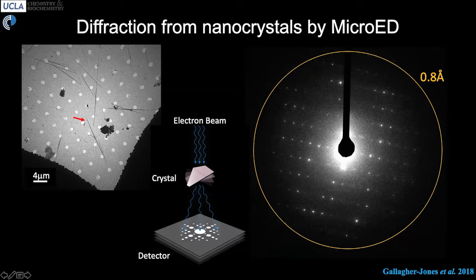It just looked like a bundle of needles in there. When we deposited them onto an EM grid, you can see a relatively clear needle crystal here. You can also see there are other things on the grid. So there's some seemingly amorphous material here. There are also some fibrillar structures, sometimes even surrounding the needle crystals.